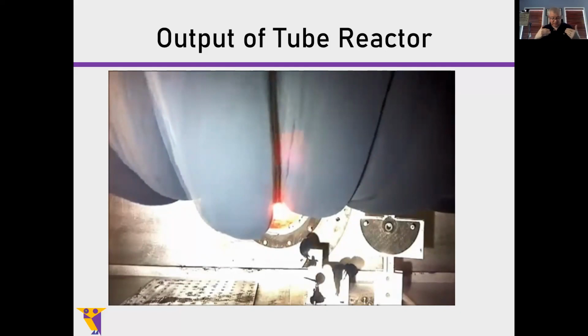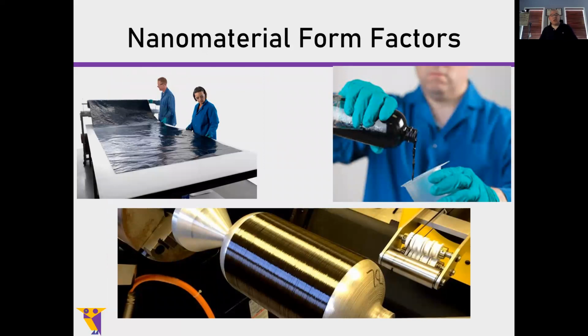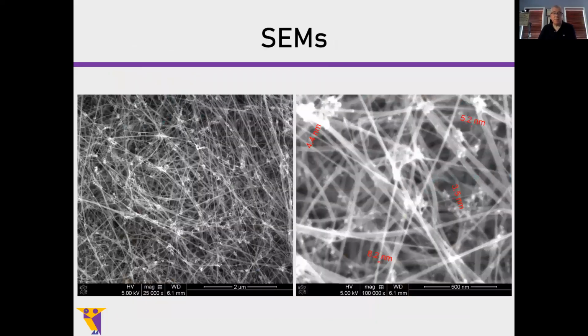And the reason for that is that this will make a filo-dough-like structure that will form a sheet. And you can see that sheet in the upper left-hand corner, one of what these sheets look like. On the right, you can see that you can also process this into things like slurries and liquids with a solvent. And thus you can mix it with things like paints, if you want to do that. And at the bottom, you can see you can also draw that sock down into a yarn or a fiber. And that is a prototype hydrogen storage tank for NASA. So this is what you can do with material that comes out of these reactors.